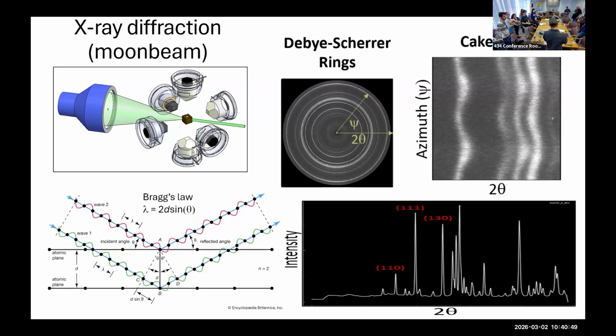Now, this one has 500 lines per millimeter. This one has 1,000. And if we look at, so this is 500, and now here's 1,000. You see how they come out at bigger angles? They're further away. So the more closely the lines are spaced, the smaller this D value, the wider the angle they diffract. So they actually call the diffracted stuff reciprocal space. So if stuff gets small in real space, like our crystal gets smaller because we're pushing on it, then in reciprocal space, the angle will get wider.